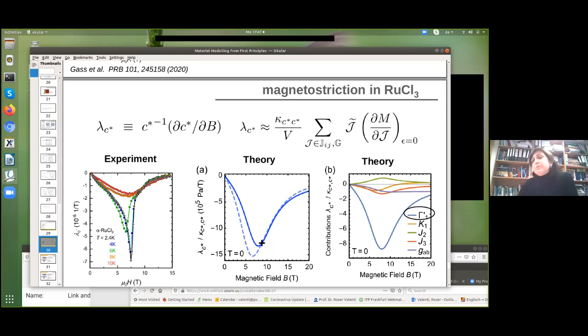The way we calculate that is we have these magnetoelastic couplings that I showed in the previous slide, how we obtain them. And this term here is calculated again with ED calculations on the spin model. Of course, because it's exact diagonalization calculations, we have finite size effects. That's why you see these roundings and not this nice sharp phase transition. But yes, the model shows also this phase transition.